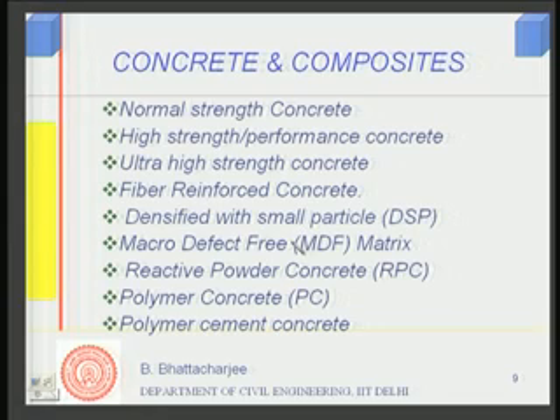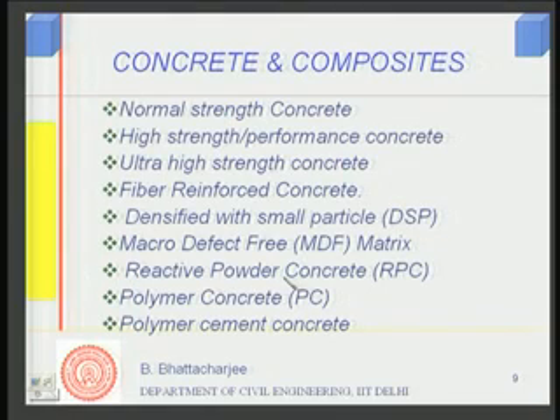The macro defect free matrix again has cement and a polymeric material together with materials like silica fume, and they are produced in a given manner to get a very high strength material. Reactive powder concrete also uses cement, silica fume, most commonly with quartz, and sometimes is heat treated in an autoclave to get very high strength concrete. So, these three are cement based composites that do not have large size aggregate, but the strength is very high. The strength achieved for these in the laboratory is of the order of around 800 MPa compressive strength. So, these are very high end materials, not used for structures very often, but used for mechanical parts or substrates for electronics, etc.